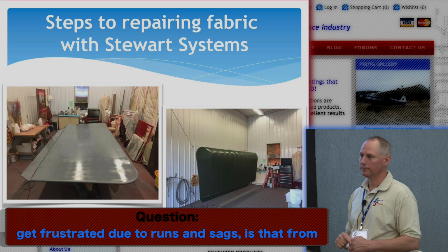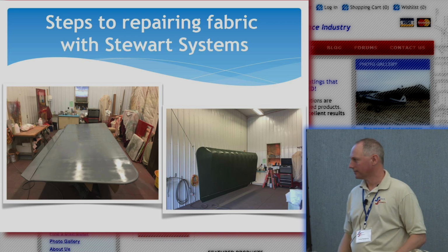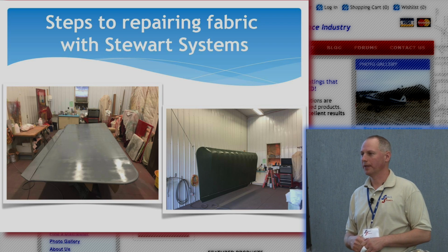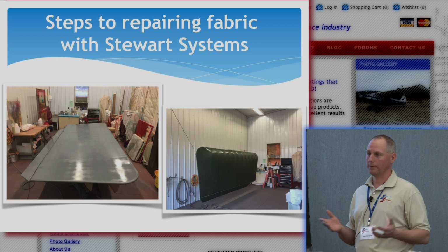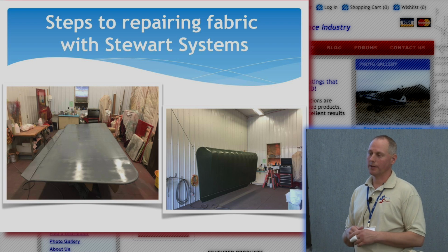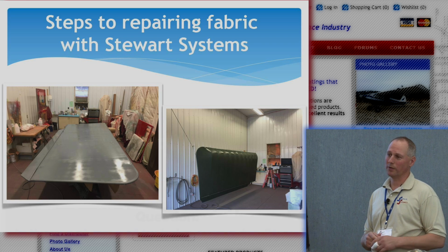Are there other questions? I've got a couple people who covered experimentals and used it all the way to the top coats on the Stewart. A lot of them get frustrated because of runs and sags in the paint. Is that just from being used to spraying solvent-based paints and the dry time and things like that? Yeah, most people used to solvent paints put our paint on way too heavy. Our paint goes on really light, and because of that, we're really lightweight in our system. If you take a Super Cub, the fabric and all the coatings and everything comes out to about 30 pounds. So we're considerably lighter than I think anybody except maybe Oratex.